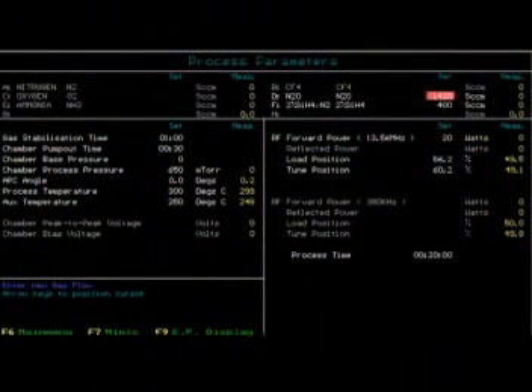There are two numbers that should be monitored during deposition. They are the reflected power and chamber bias voltage. The tuning network will automatically adjust the load and capacitor positions to reduce any reflected power. This number should be close to zero. Chamber bias voltage affects film quality as well as the deposition rate. This number should remain near constant with the same recipe throughout the process. If the number varies, this indicates a change in the chamber condition. If this is the case, the MRC staff should be notified.